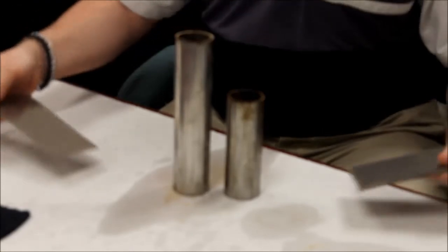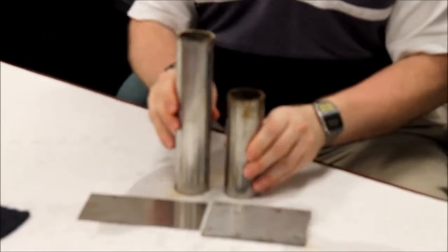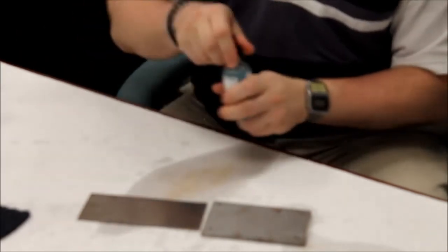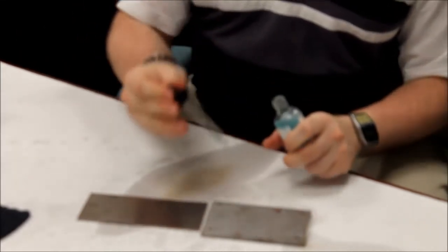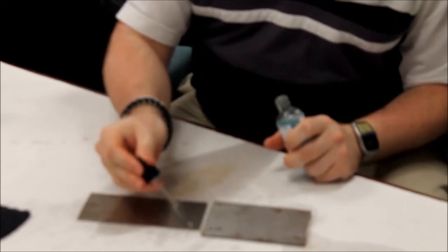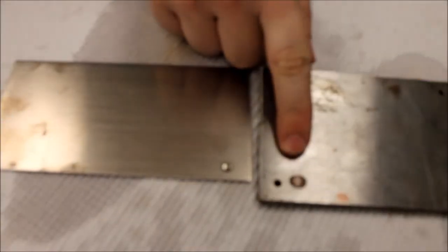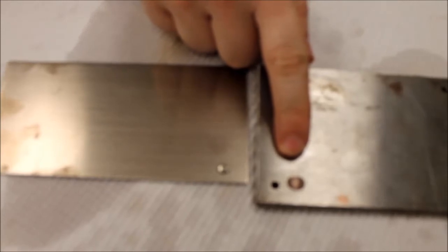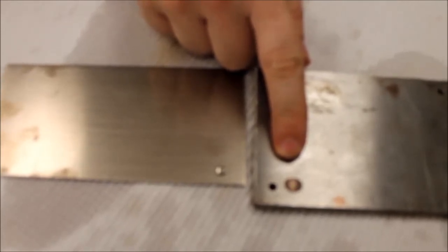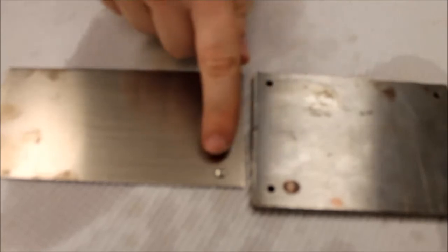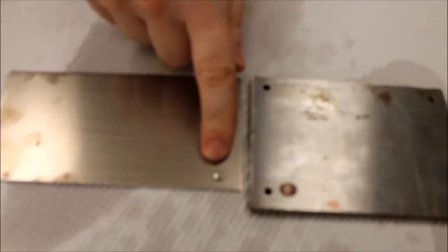Now, if there's a lot of iron on the surface, sometimes one treatment with the CitriSurf isn't quite enough to get the rust and all of the remaining iron off. You can check this using the copper sulfate test. Put a drop of the test solution on the surface. If you see a copper-colored dot forming within 6 minutes, there's still enough iron there that the rust is going to come back sooner rather than later. If there's no reaction in 6 minutes, that's considered a test pass.